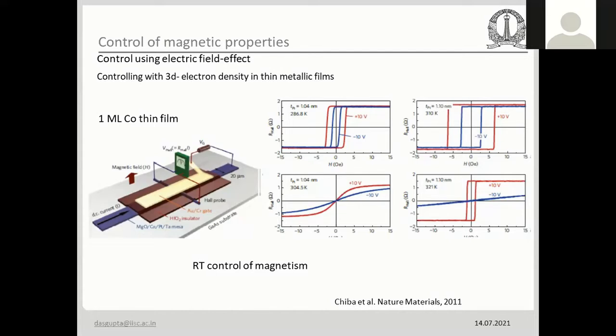And this is what the main problem is, that the good magnets are metallic magnets, right? I can control the charge carrier and I can control the material electronic property as such for a semiconductor deep into the material, for a large thickness. That's why when we talk about transistor, we don't say that the semiconductor must be 1 nanometer, because we can control the material electronically much deeper inside. On the other hand, if it is a material like a metal, in this case the 3D magnetic metals, we can only control it to 1 to 2 monolayer, very thin. That is the problem, and that's why in this example they even went for 1 monolayer of cobalt. You can imagine it cannot be less than this.